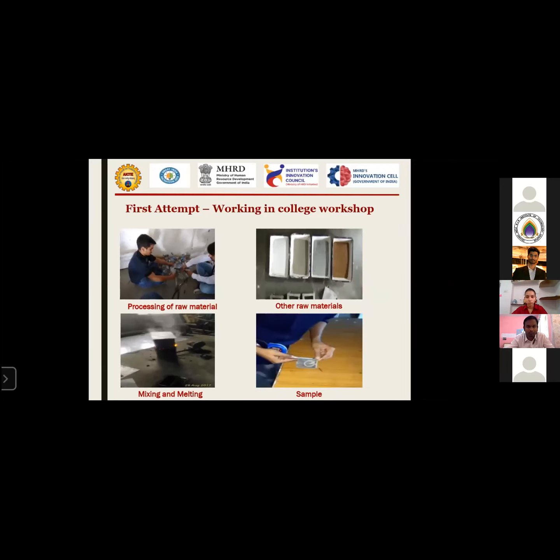Then we made small samples of 35 mm, 45 mm, and 75 mm size, and then we tested them. In our first test, we got 6 megapascal, which was equivalent to second class brick. So then we thought, okay, this can be made and this can be converted into a commercial product.